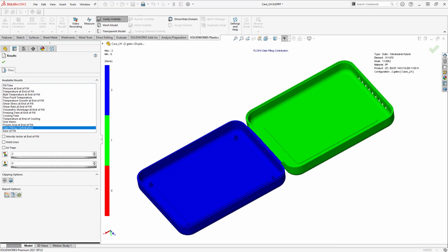Another good, easy thing to look at, quick and easy, is the gate filling contribution. When I'm looking at multiple gates on a part, this is an example of the first one I had where I had the weld line right in the center. So my gate filling contribution shows that the gate that's filling this side and the other side are meeting right in the middle of my hinge. My new gate location, when I moved the gate location on this side closer, it actually filled all the way across the hinge. So I can see that my gate location is such that they meet down here at this point now.